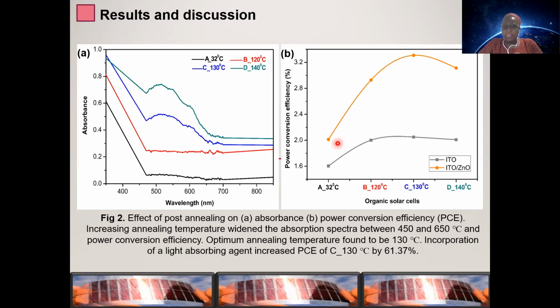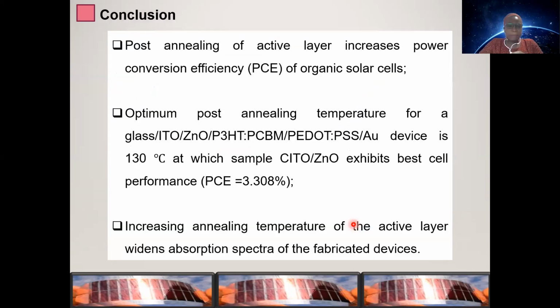So you see from here that the power conversion efficiency was increased, and the optimum annealing temperature was achieved at 130 degrees centigrade. So we have almost 61.37% improvement in the efficiency of the solar cell that was fabricated. So in conclusion, post-annealing of the active layer increased the power conversion efficiency of the organic solar cells. The optimum annealing temperature was found to be 130 degrees Celsius, compared to studies in the literature and from our previous study.